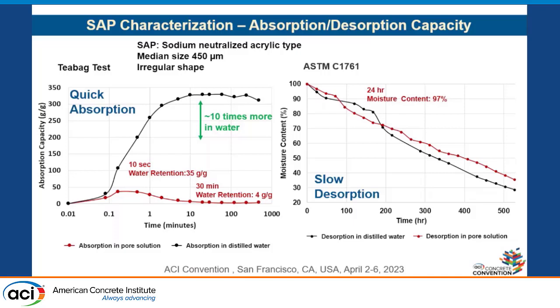Okay, we have a problem during that time because the first 30 minutes is important for us, and it seems that the SAP sucks down all the water or a lot of the water that we need for flowability and the printability of our mixtures.